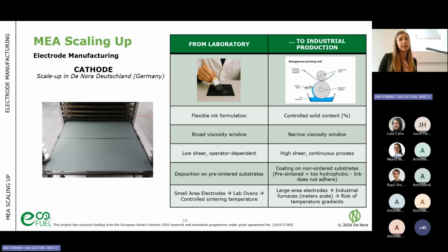And another important parameter is the oven that we are using. If we have a small area of the electrode, we can use a lab oven in which we have a controlled temperature. While in the case of the large area, we have industrial furnaces, meter scale furnaces, and we discovered that sometimes we can encounter some problems like temperature gradients. They can also be tens of degrees, and this can play a crucial role in the final sintering process.